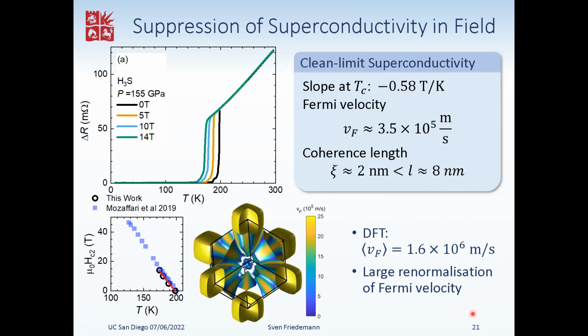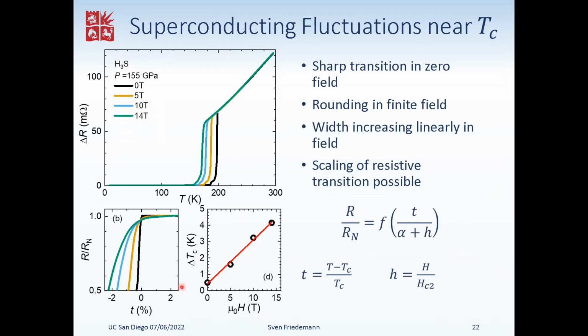You can already see a bit of the rounding of the superconducting transition. We can have a closer look at this. If we plot the transition versus reduced temperature, then you can see here that the rounding becomes quite clearly visible as we increase the magnetic field. The width could be characterized, for instance, as a temperature difference between 50% and the onset. It increases linearly in field with a finite intercept, and we've got a significant increase.